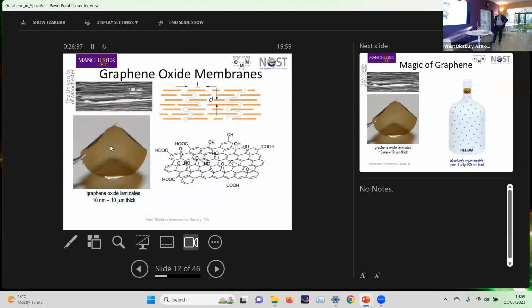Now, I just mentioned a property of graphene oxide, this material that you make by oxidizing graphene, because it's quite an interesting property, and it does play a part later on. Graphene oxide can be made into laminates. You can actually press this powder together and form these sort of laminated structures. And they have little nano channels between the layers. And these channels are quite interesting because